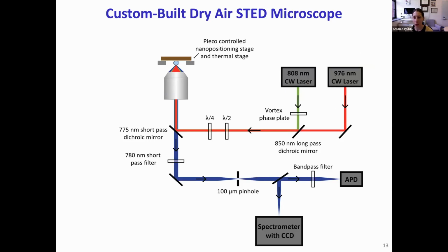Our first step was to construct a custom STED system, and I'll highlight a few particular features. We combine a 976 nanometer excitation laser and an 808 nanometer depletion laser, and these are both continuous wave laser beams. We use half and quarter wave plates to circularly polarize the depletion beam, and we send it through a vortex phase plate to generate the donut shape. We focus both beams onto our samples, which sit on a piezo-controlled nanopositioning stage and a thermal stage.